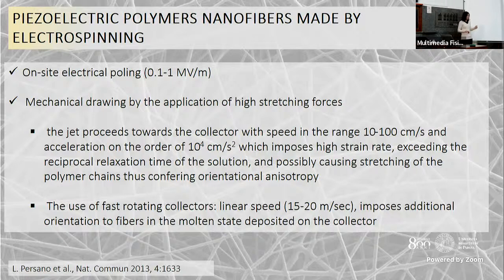It can be summarized in this slide. So, first of all, through the use of the electric field, you make an on-site poling. So, you don't need additional treatment to the material. So, you just make fibers and you apply an electric field. So, the resulting material is already poled. So, it is already piezoelectric.